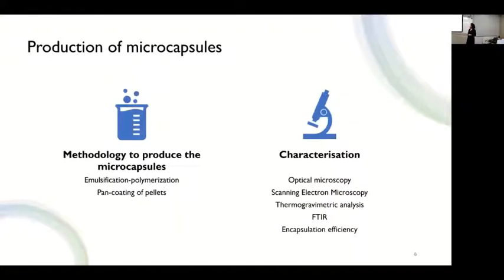is that first, there are traditionally two methodologies to produce these microcapsules, broadly speaking. Either we are talking about having a liquid core for these microcapsules, and then those are all the processes that Dave was mentioning this morning, because what you have to do is produce an emulsion of this healing agent that is going to be your liquid core, and then deposit a shell on the interface of that emulsion, and then you have that core-shell structure of the microcapsules that you want. It's either that way, or the other way, if you're encapsulating a powder or a solid core.